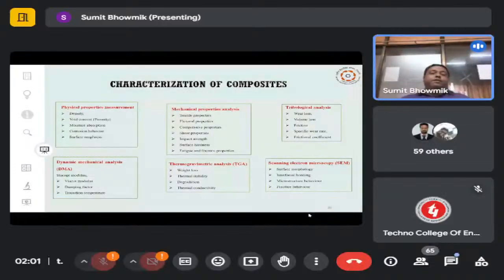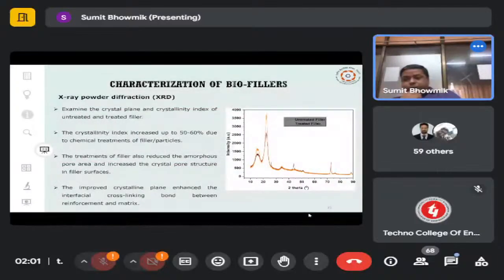For example, for physical properties, most of the testing or experimentation needs to be carried out. Then for mechanical properties, in between that we have investigated the compressive, shear, impact, or fatigue, and in some cases fatigue fracture also we have done, but not for all the cases. But in the case of tribology, because friction is most important, in my next discussion I will go through that. Then the DMA analysis, in most cases we have carried out. Then TGA analysis as much as possible, thermal conductivity and weight loss we have carried out, and microstructural study we have investigated.